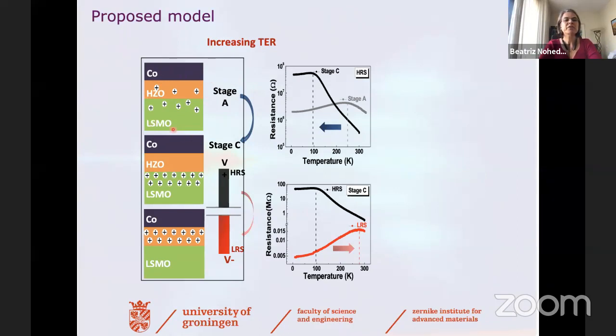In the original growth state, there are oxygen vacancies both in the hafnia layer and in the LSMO layer. And in the high resistance state, by going from stage A through cycling to stage C, all the oxygen vacancies are pushed, because of the polarity of the field, into the LSMO. By changing the polarity, the vacancies are pushed back into the hafnia. And this is creating these very different resistance states in hafnia. Now,